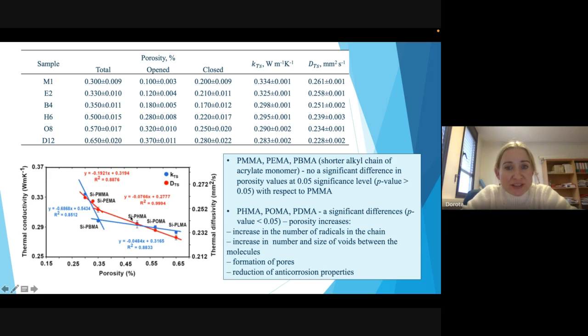But the situation changes when we increase the length of the alkyl chain of our acrylate monomer. For longer chains, hexyl, octyl and dodecyl, the values of porosity increase. Why do they increase? Because if we increase the length of the chain, we increase the number of radicals in that chain. So the number of radicals increases the size of voids between the single molecules, which in turn increases the number of pores and finally reduces the anti-corrosion properties. So the conclusion from that can be that the best anti-corrosion properties are shown by the samples with shorter alkyl chain of acrylate monomer.